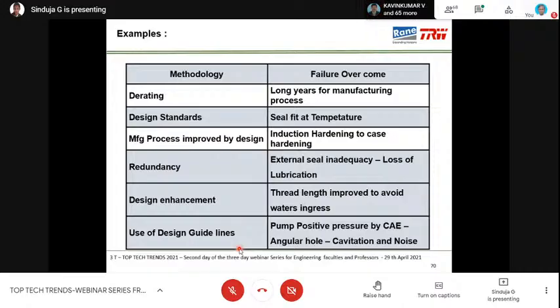Then we found that the design standard was not suiting that particular temperature application, because with the temperature change, the seal fit really changes. The interference levels are changing, stretch levels are changing. We found that the rubber is getting expanded and the seal fit is getting changed. So it was overfilling and not breathing, and we had wear out of the seal. So we applied the design standard for that, improved the design tolerances, and then we could overcome the problem.